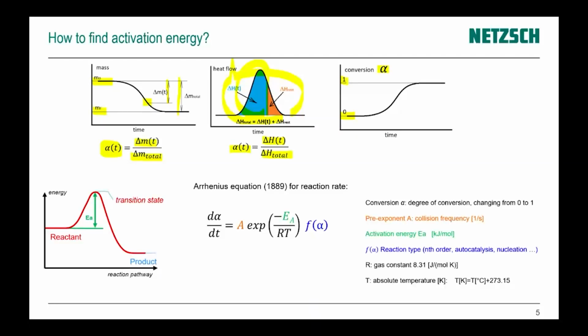And the rate of degree of conversion, or reaction rate, d alpha over dt, where alpha is conversion, has dependence on alpha, for example for different reaction types: nth order reaction, autocatalytic reaction, nucleation. Each has a pre-exponential factor, its collision frequency, and dependence on temperature according to Arrhenius.